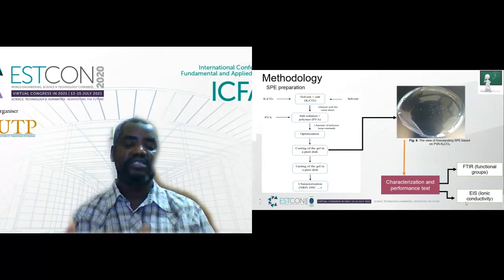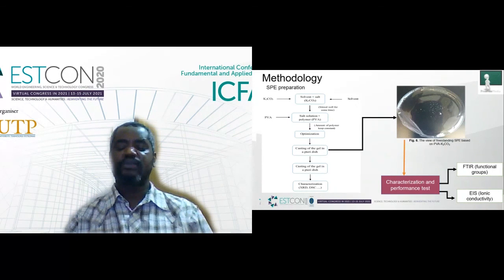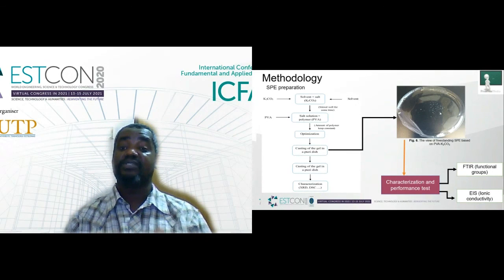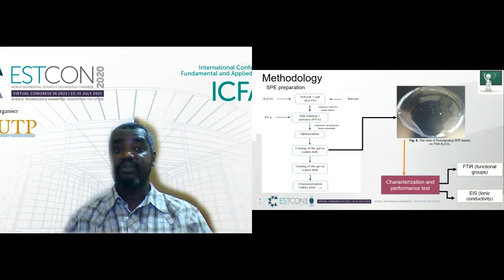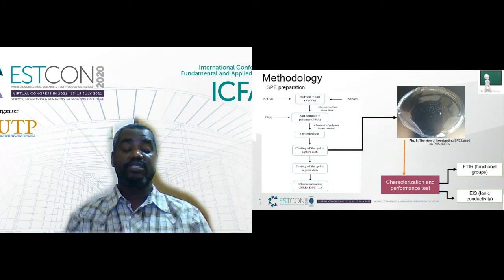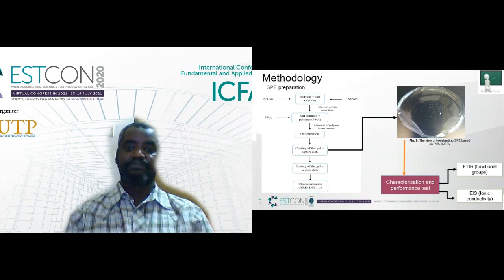Then we cast this solution in a petri dish, where we found our electrolyte to be a highly flexible and transparent material, which is ready to be used for any energy storage system. Then we move to characterize the produced electrolytes physicochemically using FTIR in order to study the functional groups between the polymer and the salt. And also we characterize the electrolytes electrochemically using electrochemical impedance spectroscopy in order to study the ionic conductivity.